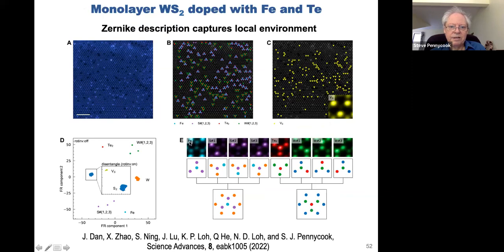Here he's locating ion dopants. He can distinguish the sulfurs next to them in 3 different positions. You can see the tellurium dopants and the tungsten. So this is tungsten disulfide. And you can see all these different dopants here, and you can also see the sulfur vacancy. So it's a very nice way to reduce the noise and automatically find the dopants.